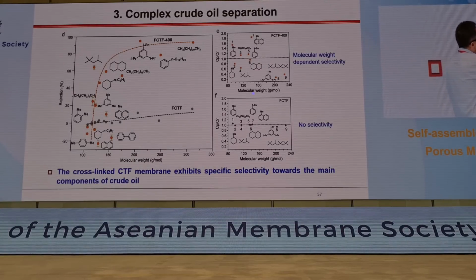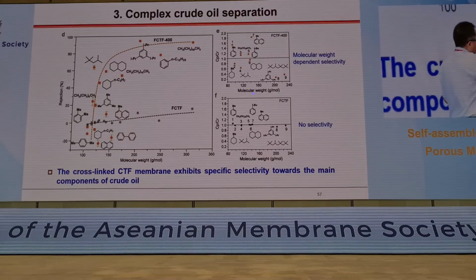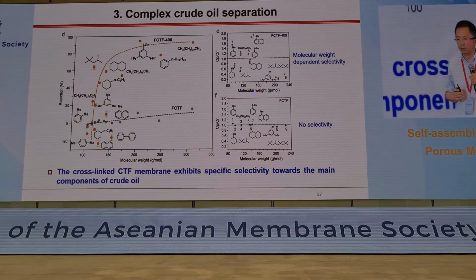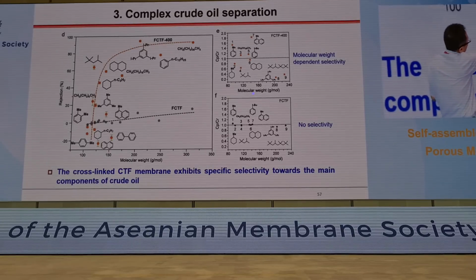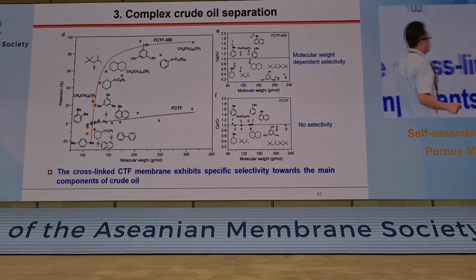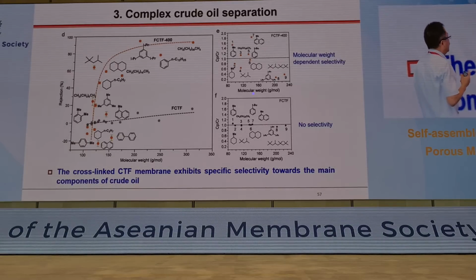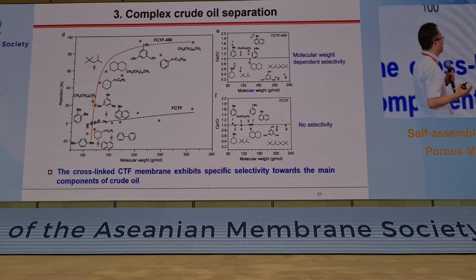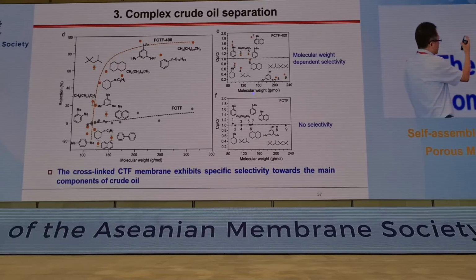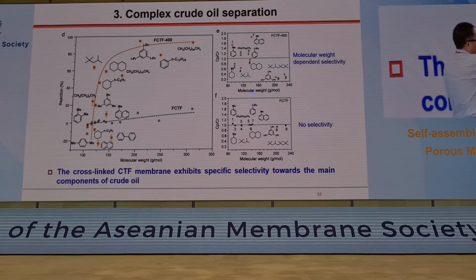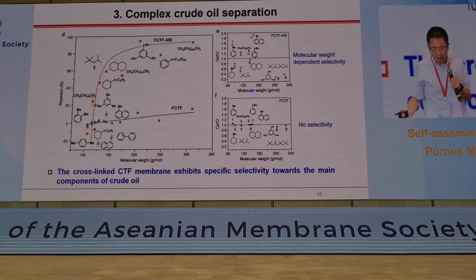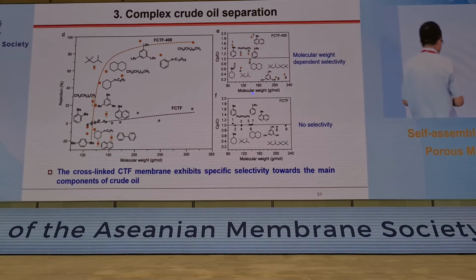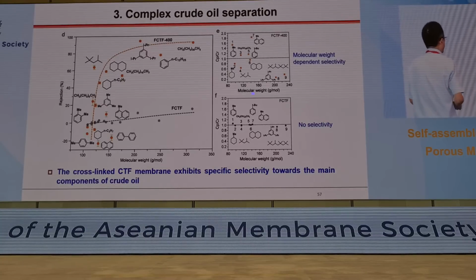So we also checked this property by using simulated crude oil, as the right part shows. We still can observe the clear molecular weight dependent selectivity. And as a comparison, we also tried the membrane without cross-link. We can see there is no selectivity obtained.